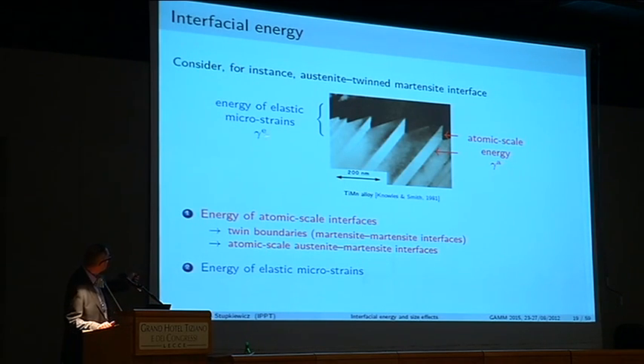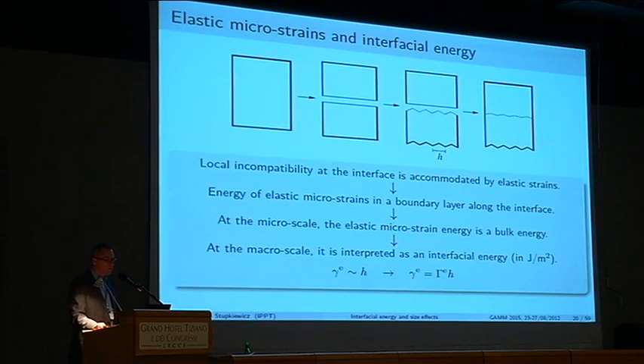There is also another kind of energy, which is the energy of elastic microstrains in the transition layer, in the boundary layer along the interface. And this is what we will look at more. So to explain more about this energy, let's do this simple experiment. We take a piece of material, we cut it in half, and then we deform the lower part in terms of a laminate with some piecewise constant shear deformation, and then we glue it again.